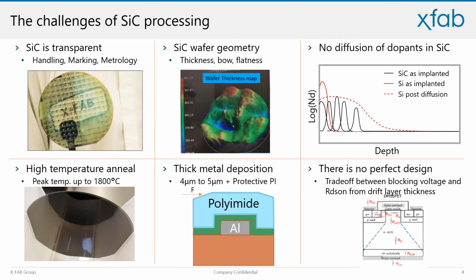As you know, we are talking about power devices, and this means a high current density that requires very thick metals at the surface. On the other hand, devices in the 600 volt up to 1700 volt need the wafer to be thin. The thinner, the better for the RDS(on). So the stress handling of the silicon carbide wafers becomes a huge issue. And last but not least, there are the challenges in the device design. There is simply no perfect design, but just carefully balanced trade-offs between, for example, the blocking voltage and the RDS(on). So to summarize it, to process silicon carbide wafers in a silicon foundry is quite a challenge.